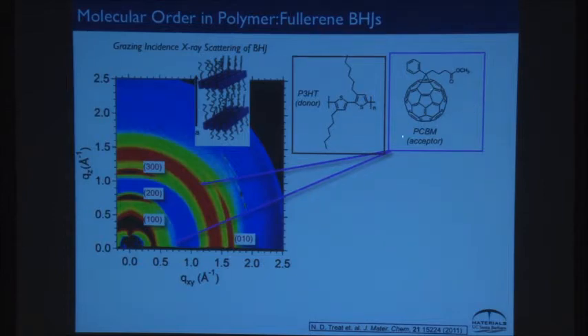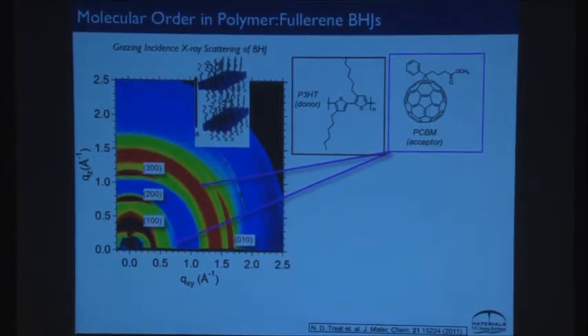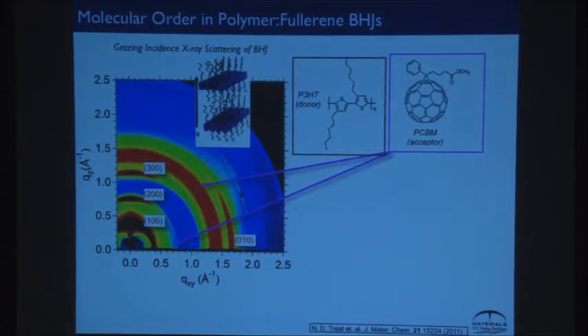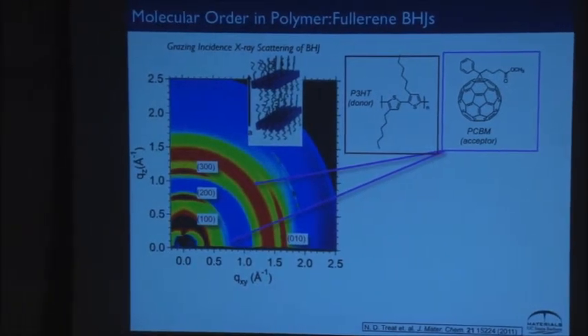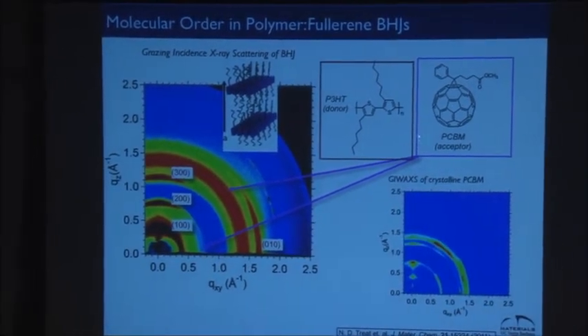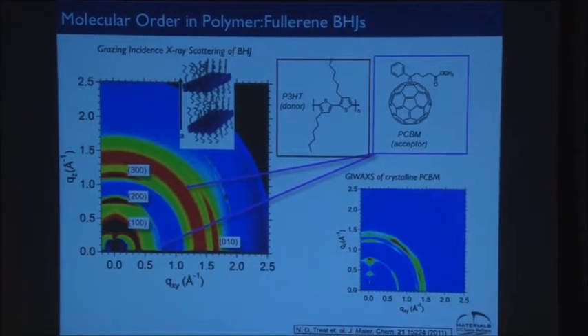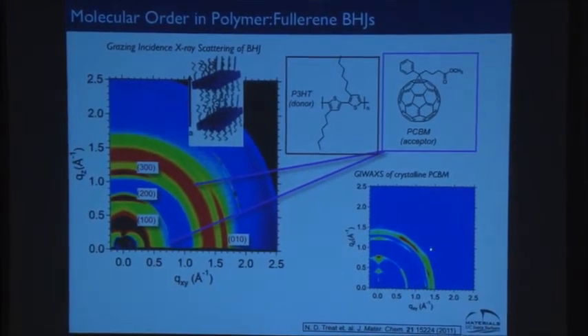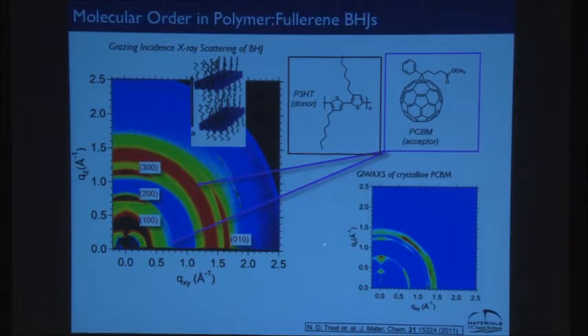So this fullerene that mixes in to the polymer ends up being amorphous. If you look at the peak width there, it's actually very broad, and you'd get a crystallite size or correlation length of only a couple of these fullerene molecules. So it's very glassy. We know this for sure because if you made a crystalline version of this material, you'd see nice diffraction peaks as well. So this would be a neat film of PCBM. You don't see a combination of that picture I saw in the previous slide and this. What you do is you see these broad rings.